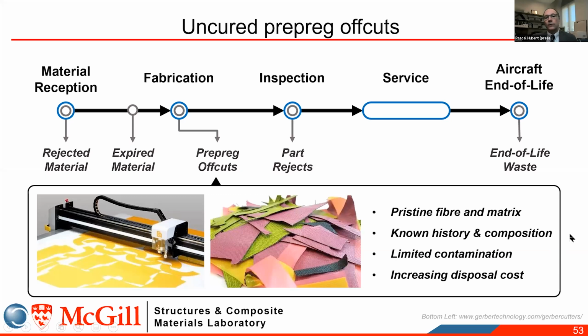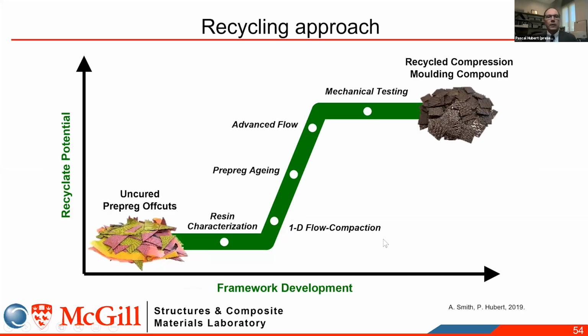Because the numbers can vary from 30 to 50% waste, it's very significant. So the approach that we developed was to take these uncured pre-preg offcuts and transform them into a recycled compression molding compound. So I'm going back to my chip idea here. To do so, you need to do some resin characterization and some flow experiments, so that you can design the right aging protocol for the pre-preg to get to this recycled compound. That's what I'm going to be showing you briefly.